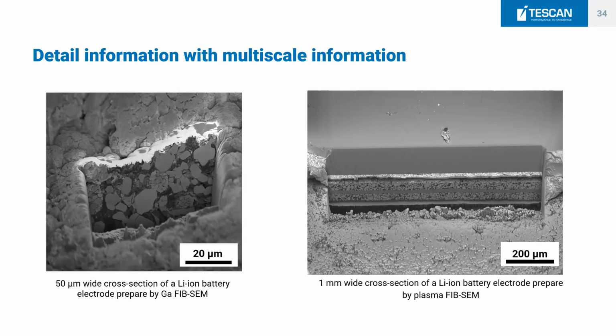And the second one is focused mainly on the nanoscale. So it can do smaller cross-sections, but it can do it way more precisely when it comes to really small nanopatterning applications, for example. And the trick here is that these cross-sections were milled in exactly the same time. So it's usually within 1 hour or 1.5 hours.